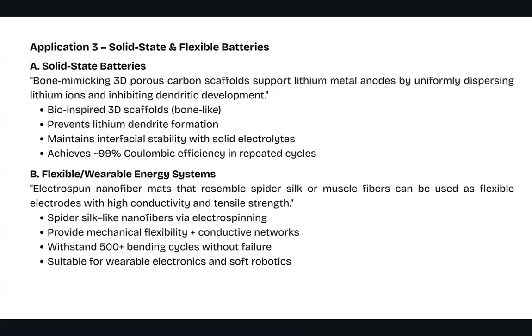And the next one is flexible and wearable energy systems. Electrospun nanofiber mats that resemble spider silk or muscle fiber can be used as flexible electrodes with high conductivity and tensile strength. The spider silk-like nanofibers made via electrospinning provide mechanical flexibility and conductive networks, and also withstand 500-plus bending cycles without failure. It is suitable for wearable electronics and soft robotics.